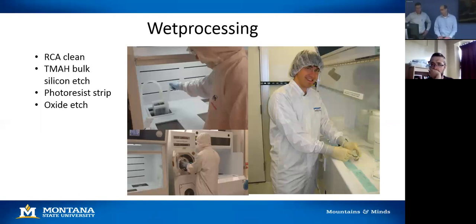We also support wet processing. All these substrates have to be cleaned before you can do a lot of these processes. So we have a lot of chemical baths, dedicated baths in some cases. Piranha, in this case, for removing photoresist. And we also have baths for etching oxides, for etching bulk silicon, and tetramethylammonium hydroxide. Then we have the spin rinse dryer. It is a washer dryer. That's what it looks like. And we also have some decks, which is deck space where people do general beaker chemistry.